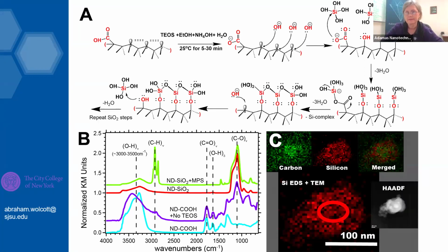So, it may end up. Yeah, maybe opposite. It could trap charge, but at the same time, maybe the frequencies of those trapped charges will be much different than dangling bonds in other groups. And so you could have boron oxygen bonds on the surface and basically minimize that spin bath by looking at different frequencies. Stuff that Natalie De Leon and others have done with the single and double quantum measurements that they had looked at in 2019. So.